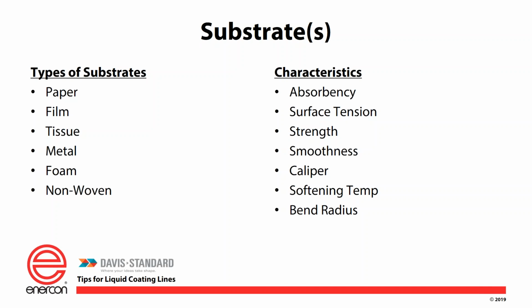That's what I'm referring to on the strength. Also on films, as the softening temp increases, films get very weak. On some, like a polyester, you can go 400 degrees and typically you don't have any issues. BOPP I mentioned earlier, about 160 F is softened. You can start stretching it and tearing it. PE, polyethylenes are like 100 degrees, 120 degrees. So we're going to look at the strength of these inversely to the softening temp of them also.